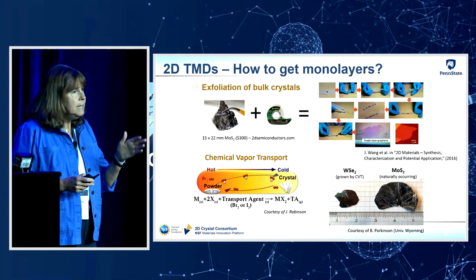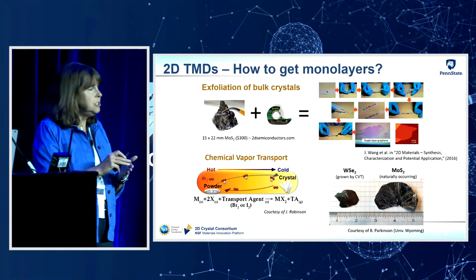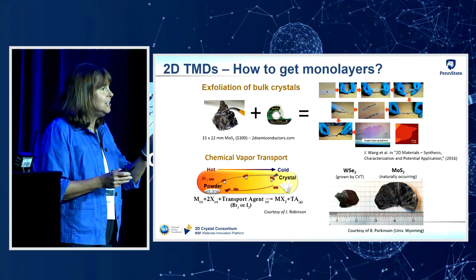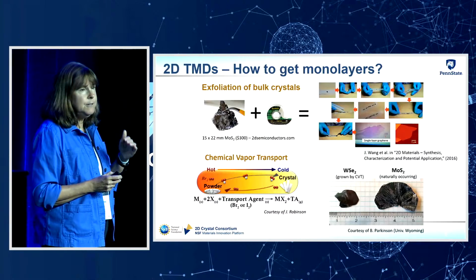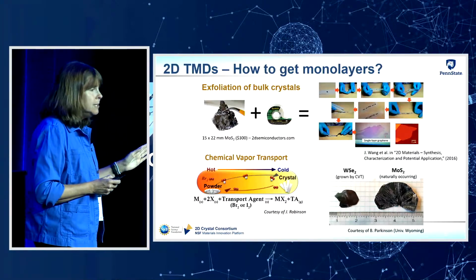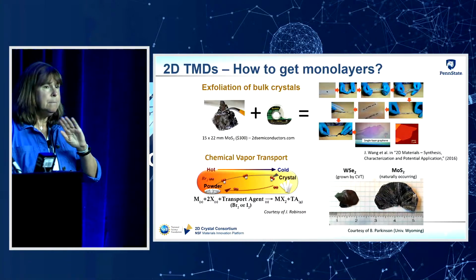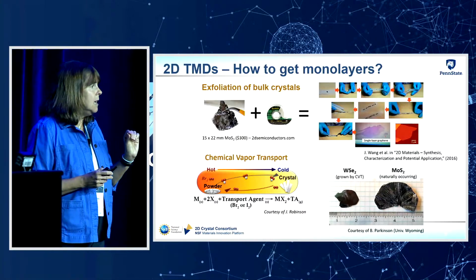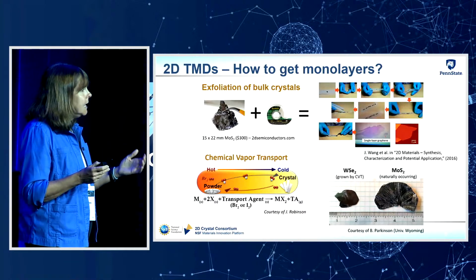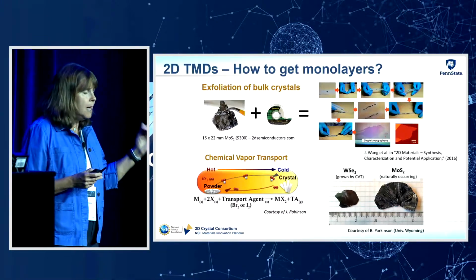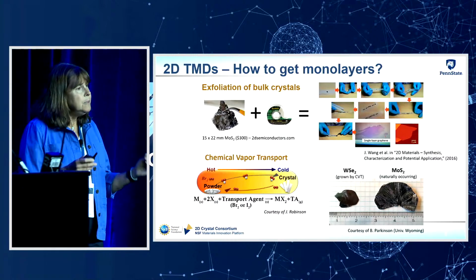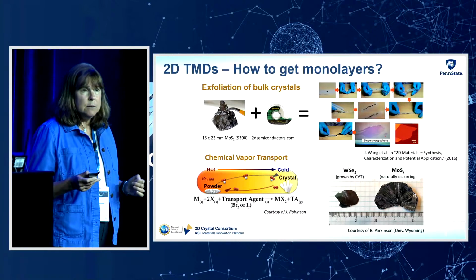So this ability to fabricate monolayers just by using Scotch tape and a chunk of moly disulfide has really made the field accessible to a wide variety of researchers. So that's been the big positive thing about the ease at which you can fabricate a monolayer TMD if you have a bulk crystal. The problem is that it's not a very scalable approach.